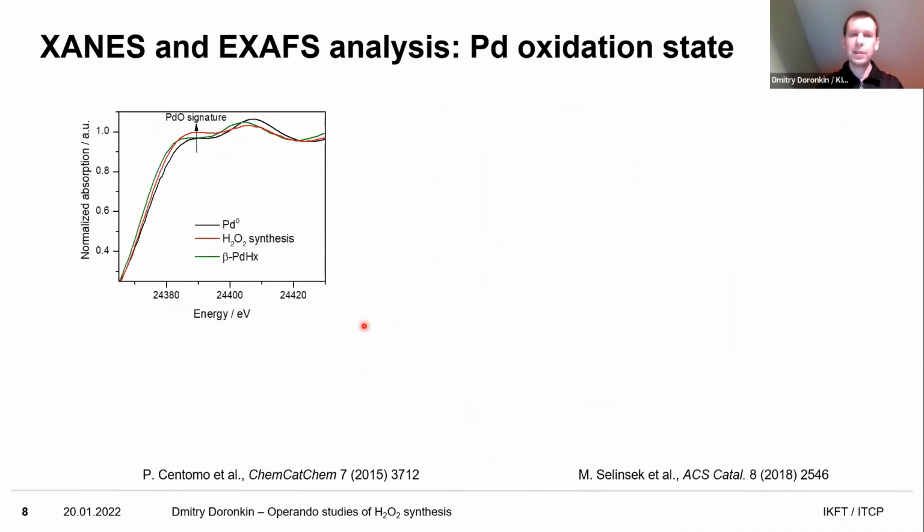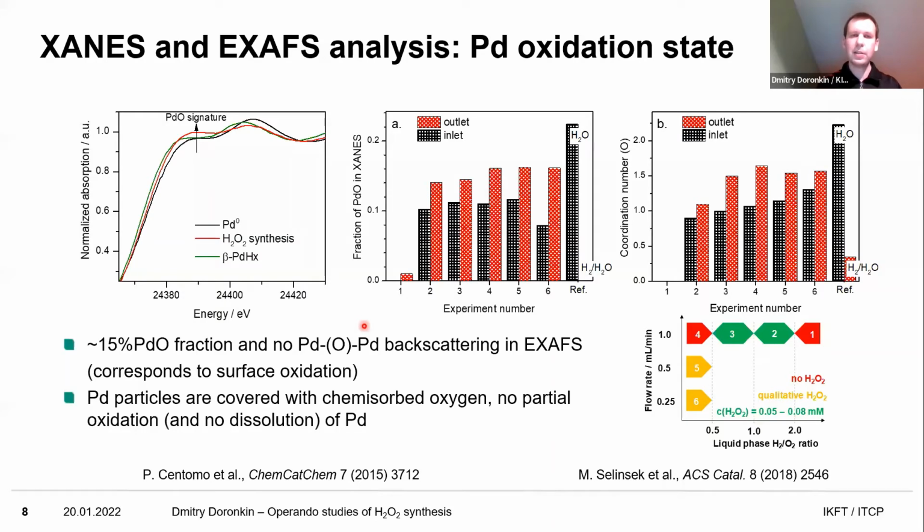So we had those references, and with the help of the references, we could quantify both. We could quantify the oxidation state, and for that we used XANES analysis, linear combination. Actually, no, I think, yeah, that was some time ago. I think we used simply the intensity at this energy point and compared to the references. And here is the data for the numerous data sets, and then the hydrides, so hydrogen saturated water reference and oxygen saturated water reference.